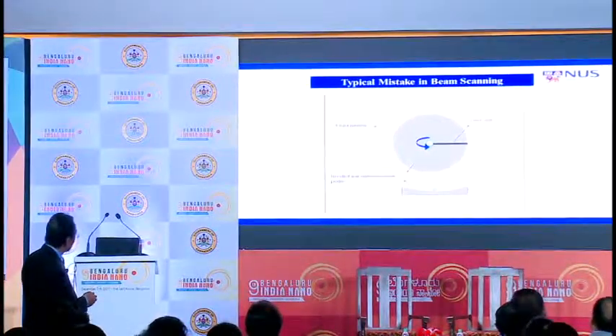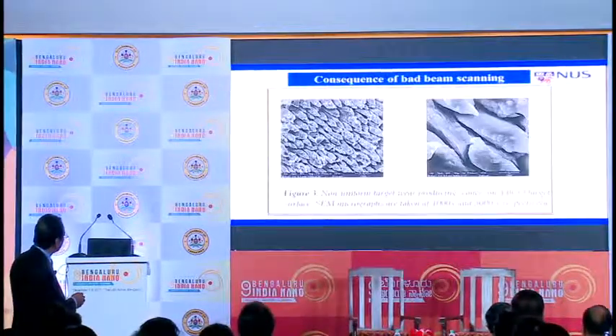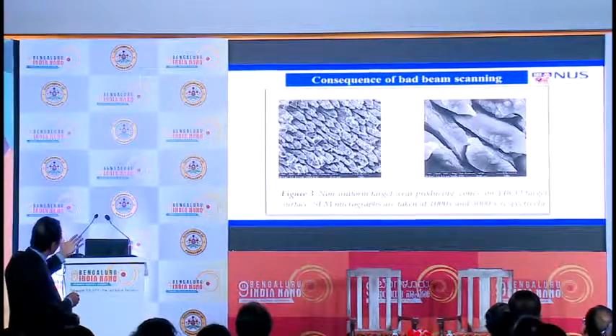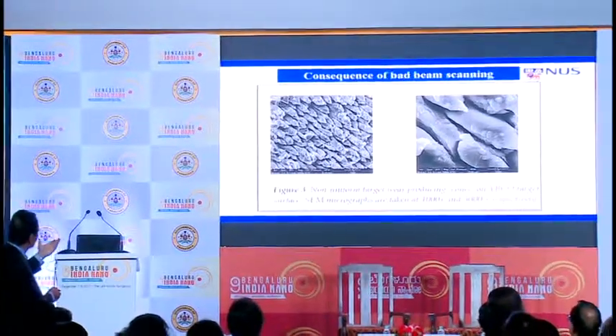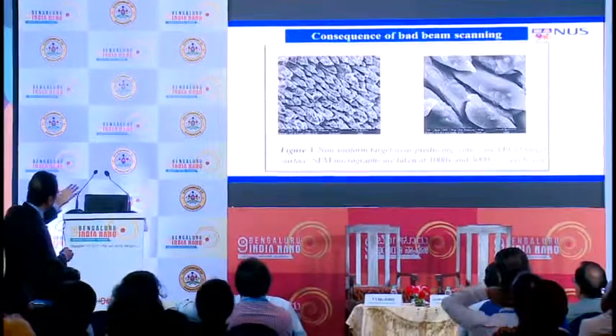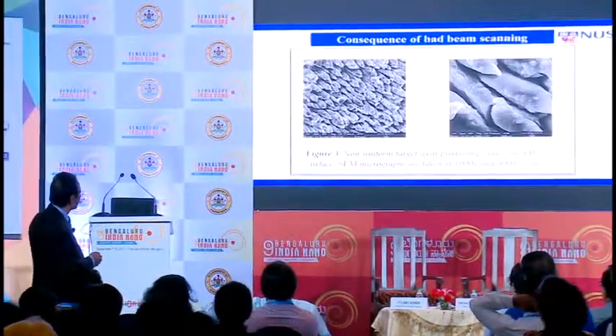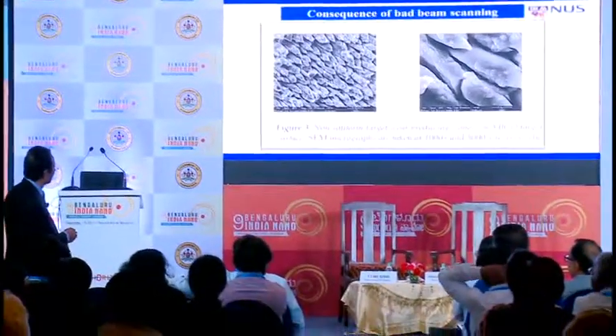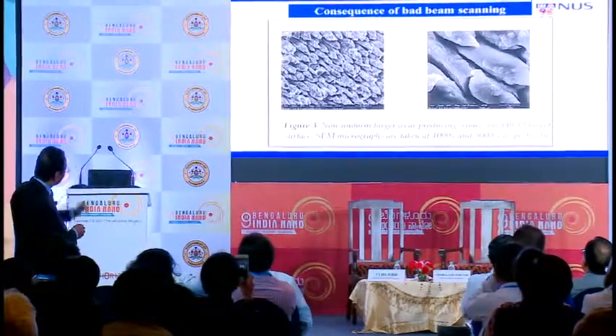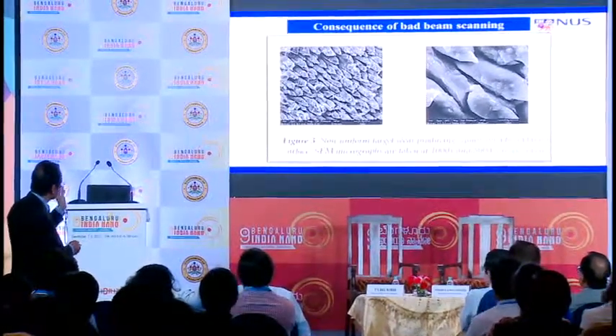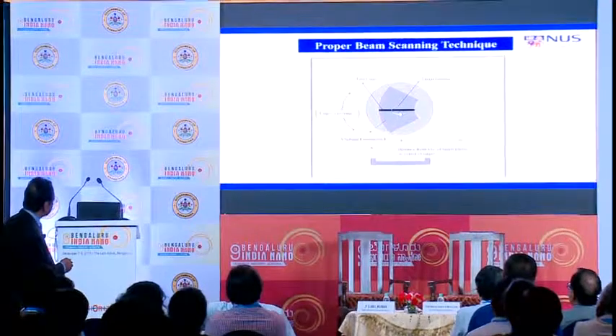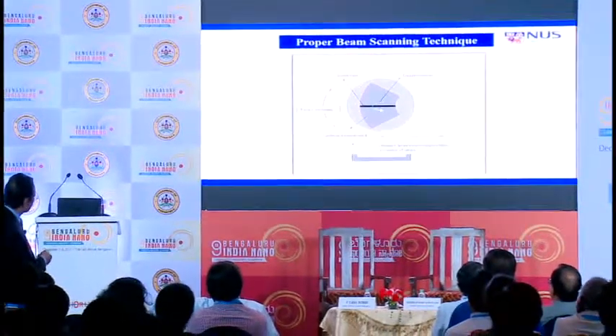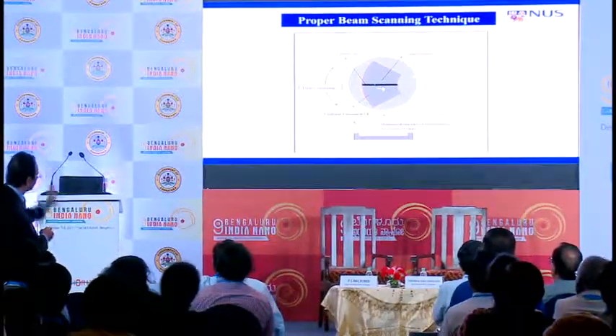The second problem is that, because the laser is coming in at an angle, any shadowing causes surface roughness enhancement. So the surface becomes very, very rough. It looks like this, and everyone has to take the target out after every deposition and sand it down. But these roughnesses produce particles in the film. Okay? So I developed a novel scanning technique, which is very different, which scans over the whole substrate.